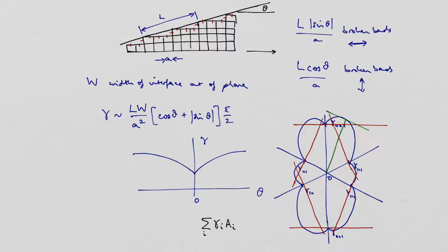Okay? And so this would say that the ideal shape of this crystal is one which is dominated by faces which are perpendicular to 111, because they are the lowest energy facets of this crystal. Okay, there is a bit of 001 there. But actually the amount that you'll get is inversely proportional to the surface energy per unit area for that particular facet.